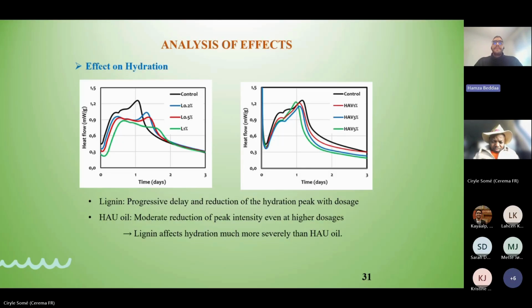So we can see that we have maybe the same effect regarding the intensity of the peak, which is that both of them reduce the intensity of the peak, but the reason behind it is different. For lignin, it's a chemical reason, which is the complexation between lignin and calcium. But for the oil, it's different. It's a physical reason, which is the hydrophobic nature and introducing air inside the cement paste.